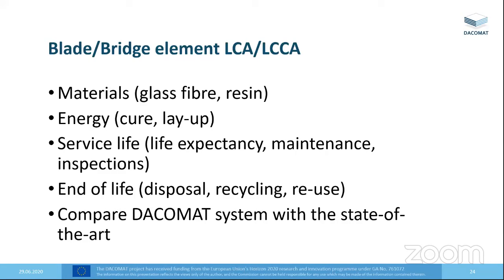The really important thing from the point of view of wind turbines in that case is the downtime. How much lost energy production because we've had to shut the blade down because of an inspection. And if we don't inspect regularly enough, do we have a catastrophic failure? That would be a much more serious amount of downtime, plus we'd have to probably replace the wind turbine blade. We also have to consider end of life. There is going to be quite an issue with wind turbine blades as they come to the end of their life, because we don't really know what to do with them at the moment.